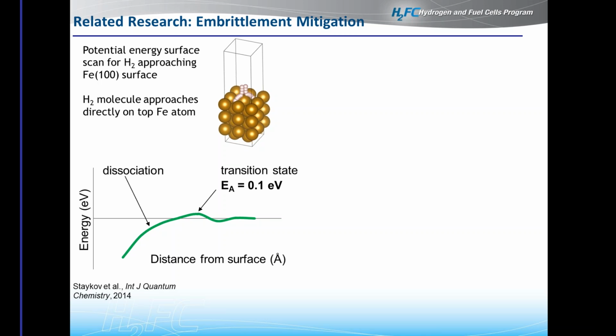Just to orient yourself, we basically looked at the potential energy. If we look at a surface of iron, so that's what these gold spheres represent, iron atoms, as diatomic hydrogen approaches the surface, there's a certain activation energy necessary for that hydrogen to dissociate and then allow it to diffuse into the surface. That's represented by EA on this curve, which is 0.1 electron volts.